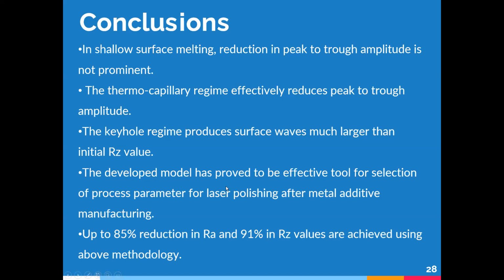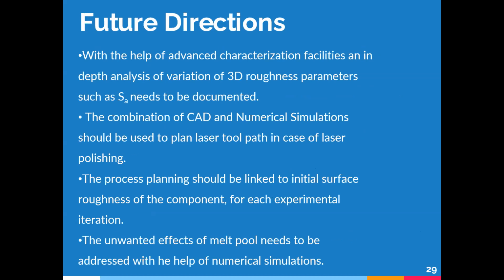So to come to the conclusions, in the shallow surface melt, the reduction in peak to trough amplitude is not prominent. The thermocapillary regime effectively reduces the peak to trough amplitude. The keyhole regime produced surface waves much larger than the initial Rz. Then the developed model has proved to be effective as compared to others. Up to 85% reduction in Ra and 91% reduction in Rz were achieved by this methodology.